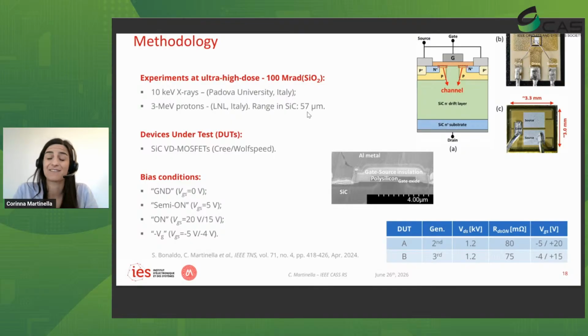These doses are extremely high, and you can only encounter them in specific applications, such as in high energy physics experiments, for example. However, when we perform the experiment, we always step the dose in different steps, so we can also get data about lower doses and observe the evolution. Just to say, for space, you are interested in regions of hundreds of kilorads.